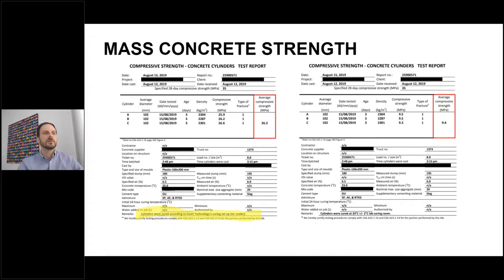Mass concrete generates significant heat, and concrete strength gain is accelerated with added heat — think of standard practice in precast production, adding heat to forms to save time. Why not take advantage of extra heat being produced in large cast-in-place elements? Using maturity, we can get real-time strength and capture the heat the concrete is generating. We can replicate what's happening on site using wireless loggers and a cloud-connected curing box that downloads site temperatures and matches the temperature of test cylinders to the actual concrete on site. Lab results confirm this: with the same concrete mix, cylinders matching the real temperature of a mass slab hit 26.2 MPa at three days, while typical lab-cured cylinders achieved only 9.4 MPa.